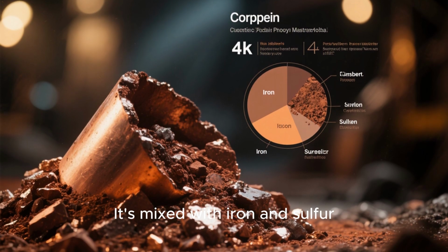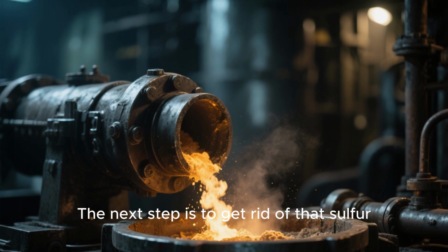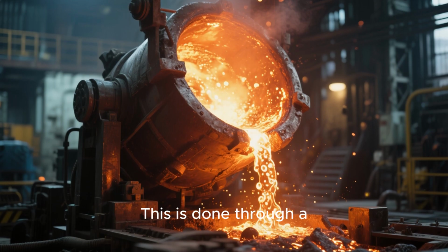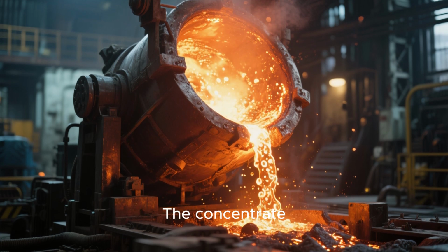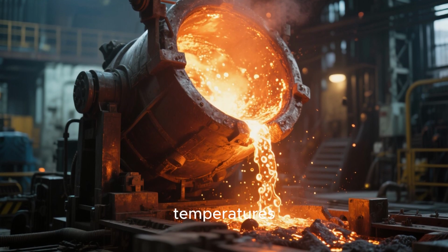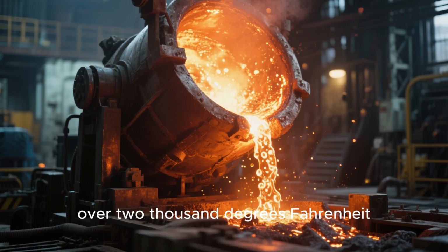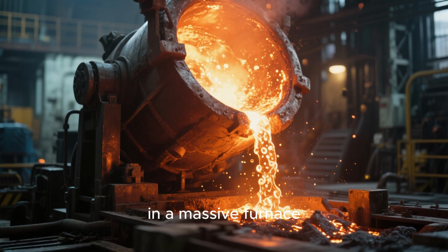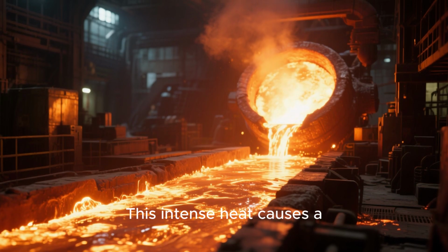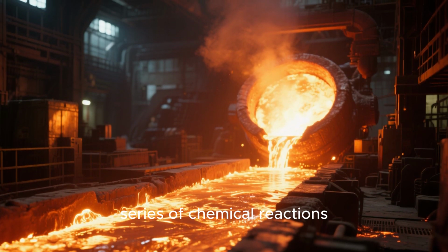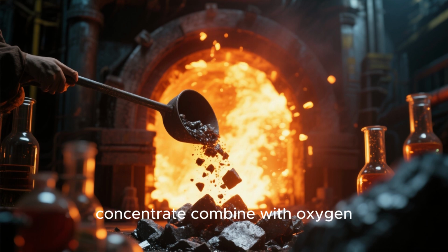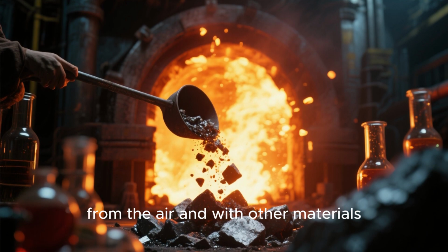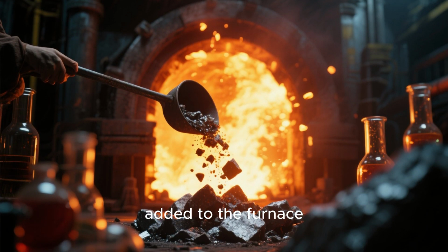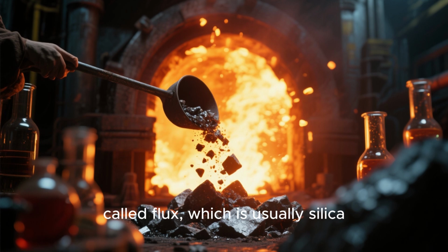Now we have a much richer concentrate, but it's still not pure copper. It's mixed with iron and sulfur. The next step is to get rid of that sulfur. This is done through a process called smelting. The concentrate is heated to extremely high temperatures, over 2,000 degrees Fahrenheit, in a massive furnace. This intense heat causes a series of chemical reactions. The iron and sulfur in the concentrate combine with oxygen from the air and with other materials added to the furnace, called flux, which is usually silica.